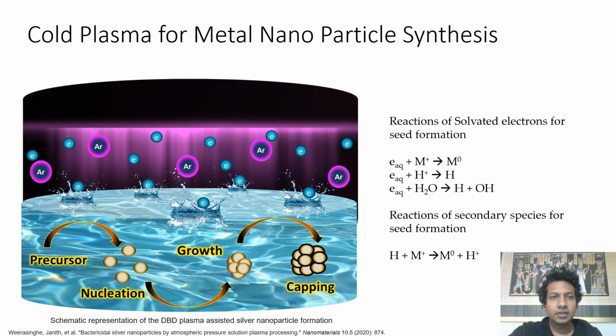Cold plasmas can easily reduce noble metals such as silver, gold, and platinum into their nanoparticle form. Metal ion to metallic nanoparticle reduction takes place due to the injected electrons from the plasma in the form of solvated electrons, or by secondary reactions leading to the metal ion reduction. Later, diffusion and aggregation of the metal atom clusters results in nanoparticle formation.